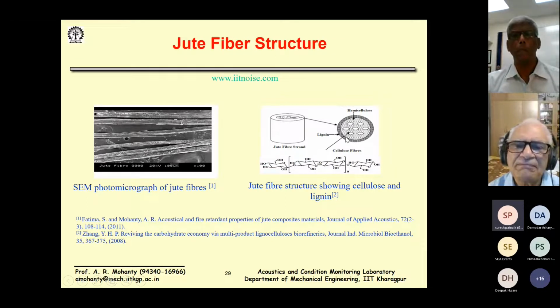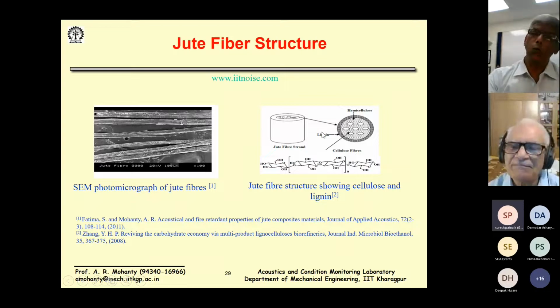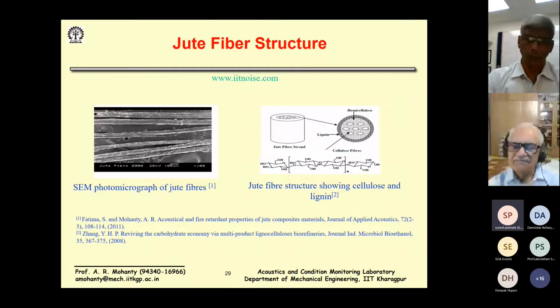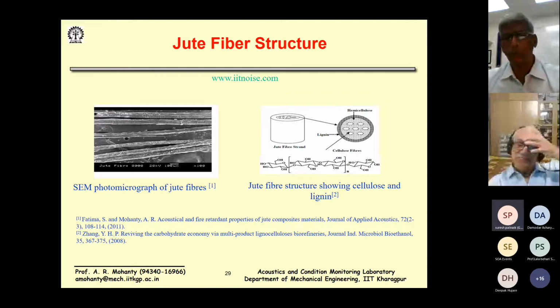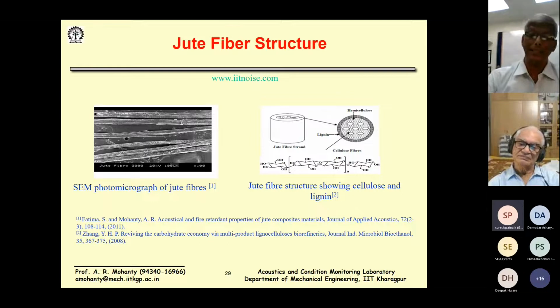And this is just to show the lignin which is there on the strand of the jute fiber. And because see, jute loves water, if you have seen, jute plants grow on the river banks of river Ganges, and when the Ganges overflows, the jute fields are flooded, but the jute does not decay or disintegrate.